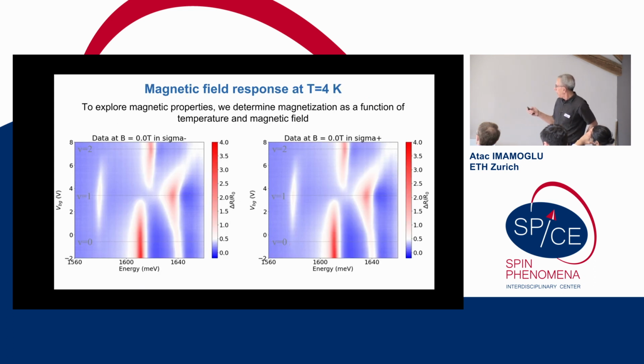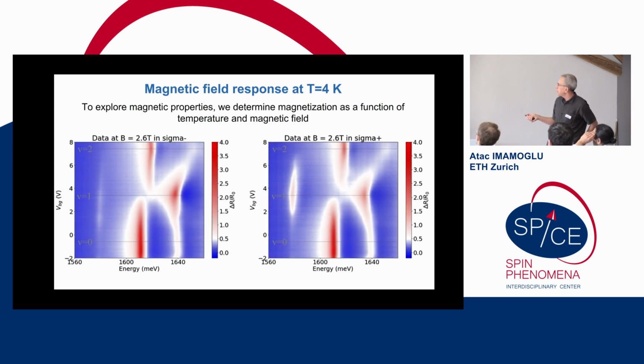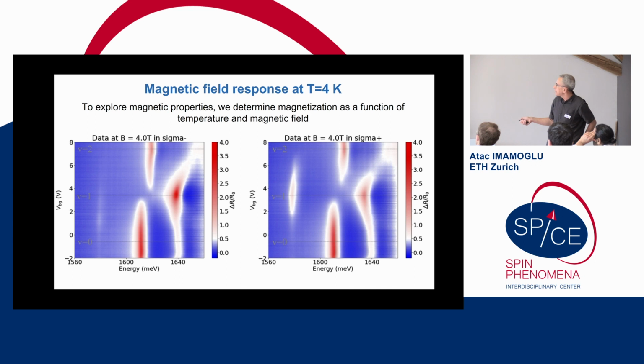Now, a movie about what happens as we increase the magnetic field. Not surprisingly, again, in this case only up to 4 Tesla, just as in the monolayer case, you see that it is the attractive polaron resonance that is basically retained only in one polarization. You see modification of the other resonances, but it's mostly line shifts rather than oscillator strength shifts.